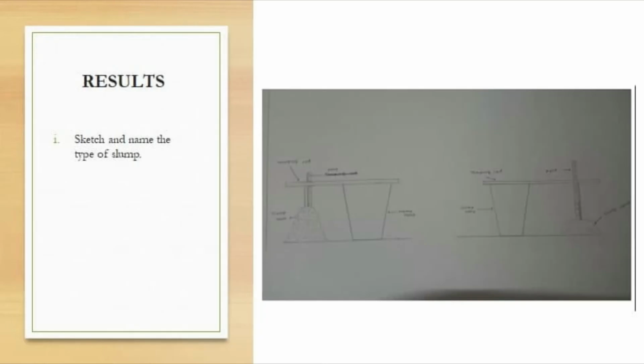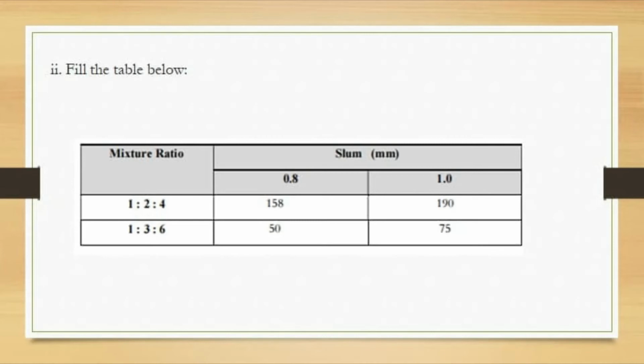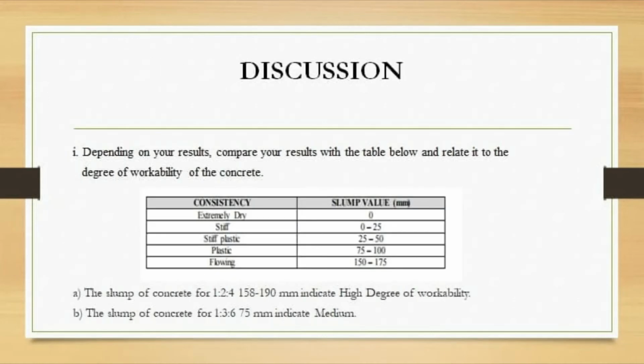Hello, my name is Nurin Shafika. So, as you can see, this is the result of slump test. I'm Imelda, I will present about discussion. Question number 1. Depending on your results, compare your results with the table below and relate it to the degree of workability of the concrete. A. The slump of concrete for 1 to 2 to 4, 158 until 190 mm indicates high degree of workability. B. The slump of concrete for 1 to 3 to 6, 75 mm indicates medium.